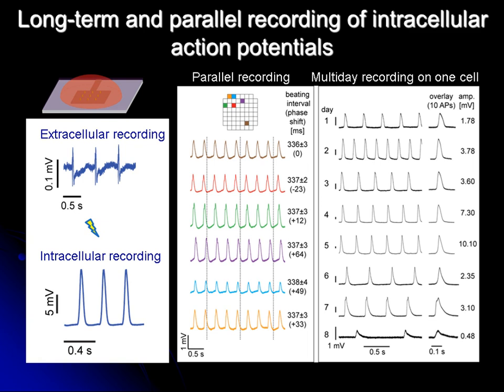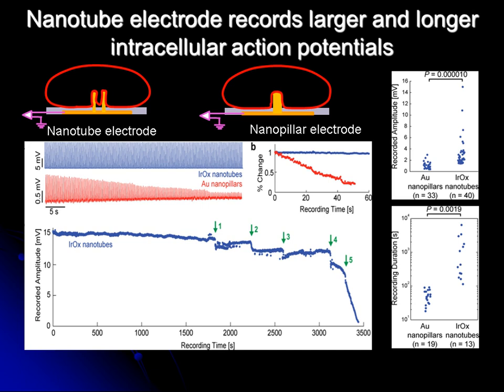So using the nanotube recording, we did very similar to the nanopillar recording. We cultured cardiomyocytes on it. We noticed there is a membrane wrapping around it. It is extracellular recording before electroporation. After brief electroporation, it becomes intracellular recording. It achieves similar advantages as the nanopillar electrode. First of all, it can do parallel intracellular recording. We can do about 60 cells at a time. Another advantage is the multiple day recording on the same cell. In the right plot, we see the same cell intracellular recording for 8 consecutive days. Those are the same advantages as a nanopillar electrode, and what is the difference?